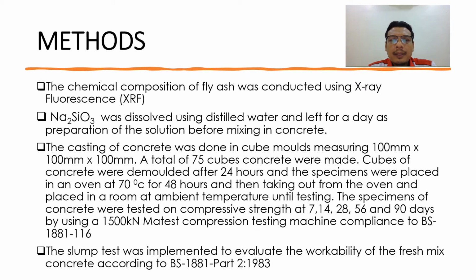This is the method of work conducted in this research. The chemical composition of fly ash was determined using X-ray fluorescence, XRF. Sodium silicate was dissolved using distilled water and left for a day as preparation of the solution before mixing in the concrete. The casting of concrete was done in cube molds measuring 100 mm × 100 mm × 100 mm. A total of 75 concrete cubes were made.